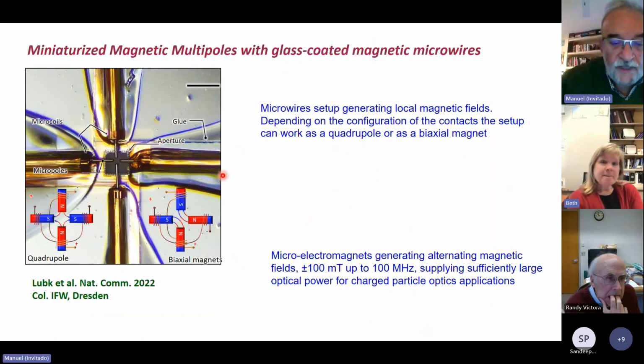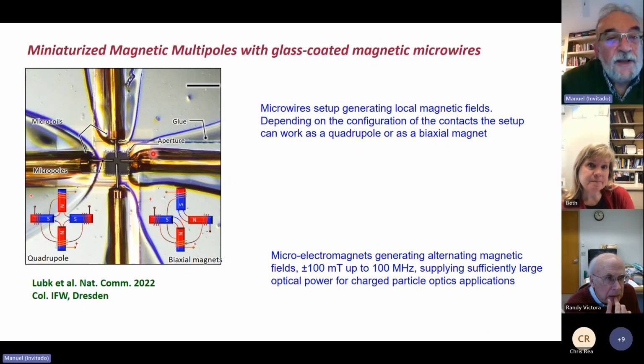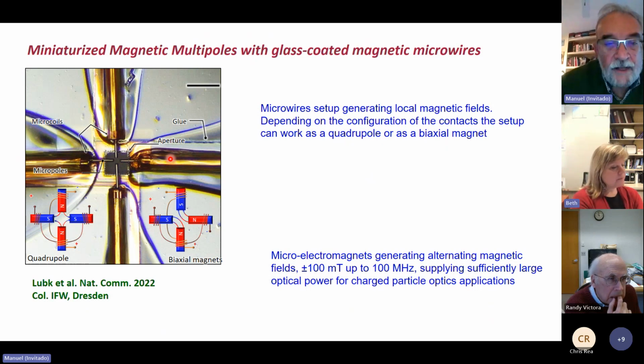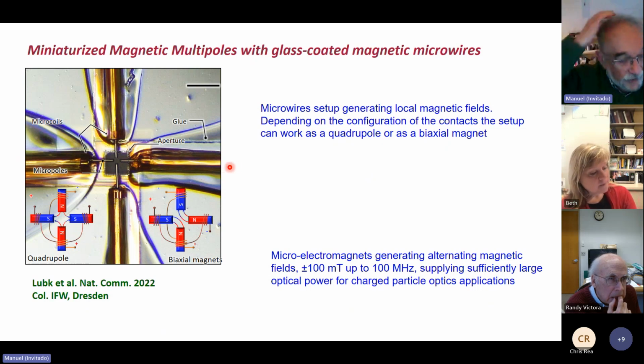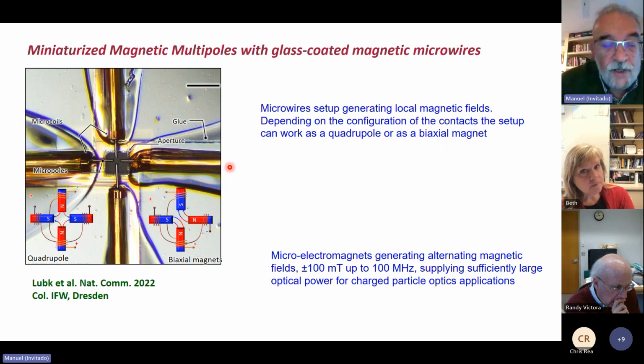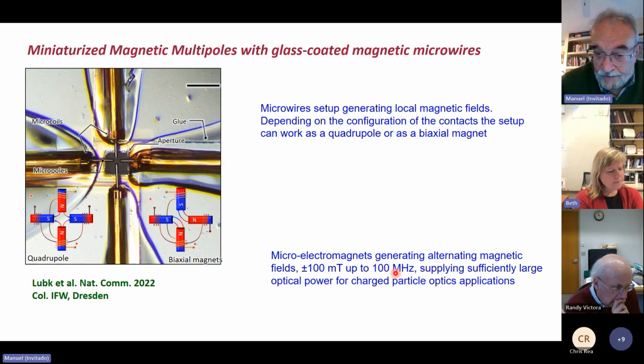Yeah, that one. Okay. So these microwires are glass-coated microwires with a diameter, I don't remember exactly, between 5 and 10 microns. And the length, I think it's on the order of maybe 1 centimeter, or at least some millimeters. So it is possible; you see here to the right, the amplitude of the magnetic field, and up to 100 megahertz.